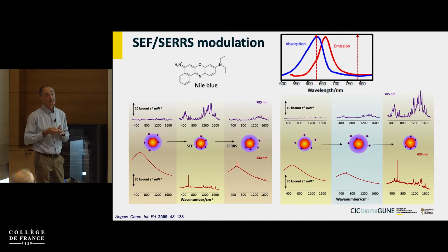So this is a sort of concept for a reusable Raman enhancer, which can capture molecules that will not bind to the core, and then release them, ready to be used again. If the molecules are remaining on the core, then, as I showed you in the previous slide, you have the problem of the memory effect, because they will always stay there.